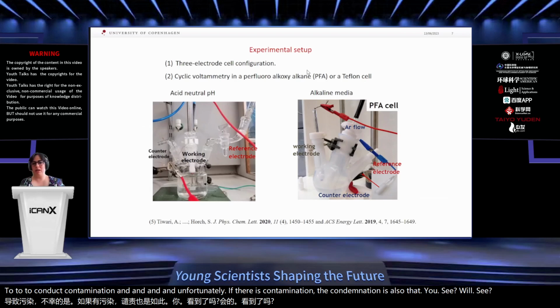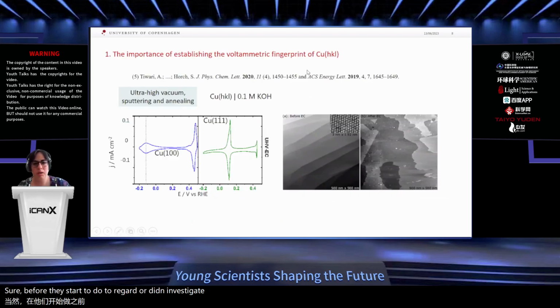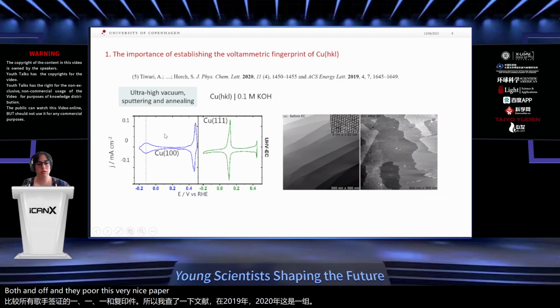So before starting to record or to investigate the voltammetric fingerprint of copper 111 and copper 100 single crystals, I checked the literature, and in 2020, this group of people published a very nice paper in which they report the voltammetric fingerprint of copper 111 and copper 100. Here you can see what a voltammetric fingerprint is. A voltammetric fingerprint is just a blank CV whose shape, intensity, and position in potential is very different for each single facet. And this allows us to differentiate different single facets.